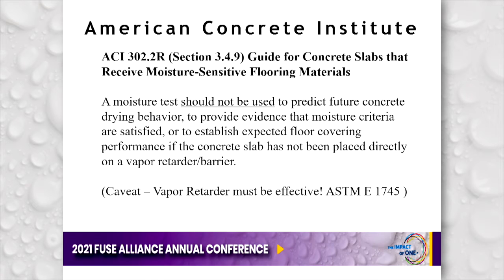Beyond the flooring industry, the American Concrete Institute has taken a position. In one of their guides, they are making the point that a moisture test should not be used to predict future concrete drying behavior, to provide evidence that moisture criteria are satisfied, or to establish expected floor covering performance if the concrete slab has not been placed directly on a vapor retarder or barrier. That's their wording. My caveat to that is that vapor retarder must be effective. It must meet ASTM E1745.